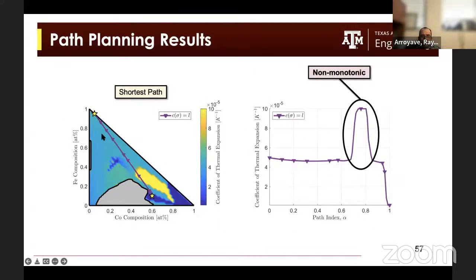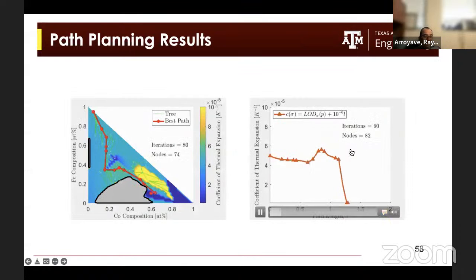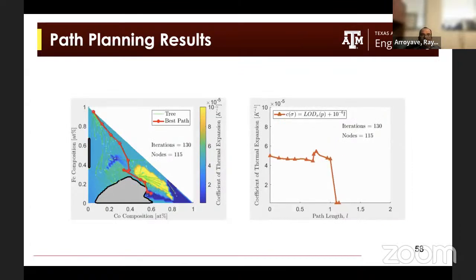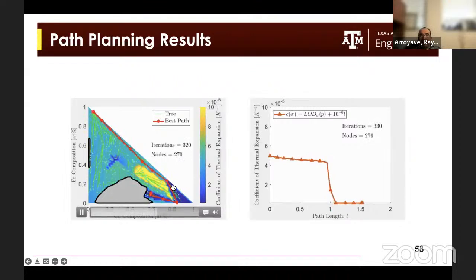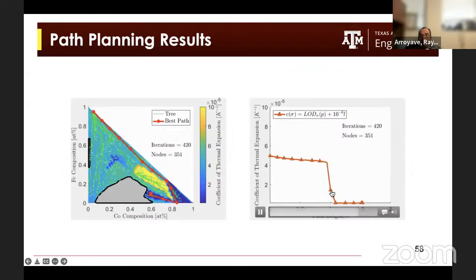So this is basically an example when we do the path planning with the shortest path. We may be able to avoid the sigma phase, but unfortunately the thermal expansion coefficient changes in a non-monotonic way as a function of composition, right? When we apply the path planning and we enforce the monotonicity constraint, what we find is that the algorithm is able to find a more complex and longer path, but in this case the property is monotonic.